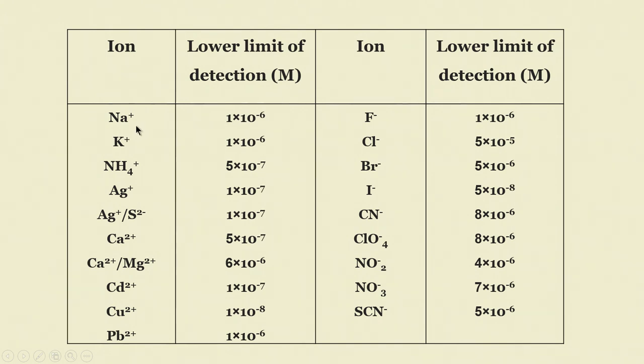Normally ppm level concentrations are of the order of about 10 raised to minus 4 or minus 5. So, molar. Sodium can be determined in 1 into 10 raised to minus 6 molar concentrations. Potassium is almost the same. Ammonium is still lower, 5 into 10 raised to minus 7. Silver is again 1 into 10 raised to minus 7. The silver sulfide electrode is almost the same, and calcium 5 into 10 raised to minus 7 molar. You can convert this into ppm by simple calculations.